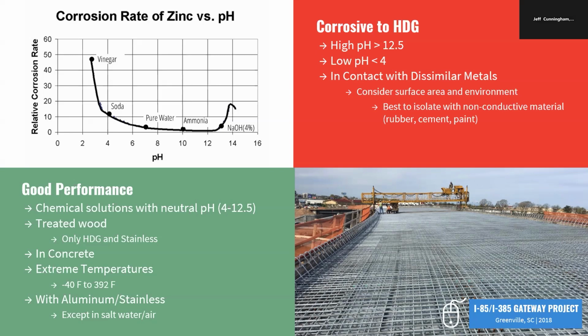Good performance is chemically neutral solutions, pH level 4 to 12.5. Treated wood: stainless and hot dip galvanizing does great with treated wood. Hot dip galvanized rebar, reinforced steel, is amazing. It actually protects the concrete from outgassing, spalling, cracking. It's really great. We do a full rebar seminar as well, and you can find a wealth of information, but it does great in concrete. Extreme temperatures all the way down from -40 to 392 degrees Fahrenheit. And then with aluminum and stainless, except when you're right off of the bay of salt water and air, that can accelerate some of that corrosion between aluminum and stainless.